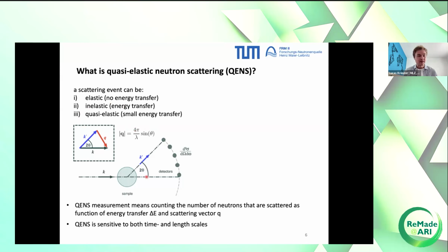And this also means that QENS is sensitive to both a time and a length scale. So time scale meaning how fast are things moving inside your material, your sample, you get out of the energy transfer, and the length scale information you get out of the scattering vector Q. And this is a really great advantage of this technique.